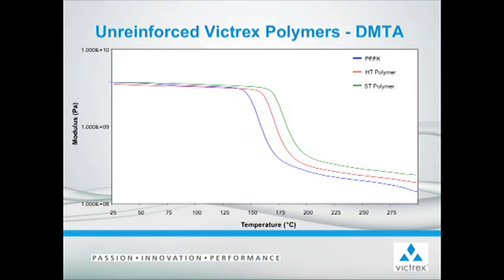This plot illustrates the difference in the glass transition temperatures of our PEEK, HT, and ST polymers. The curves are measured on a DMTA, or Dynamic Mechanical Thermal Analysis machine. The glass transition temperature is a range over which the material softens into a viscous liquid or a rubbery phase. Amorphous materials typically just get more and more fluid above their glass transition, while semicrystalline materials like PEEK, HT, and ST will maintain mechanical properties and stiffness above the glass transition all the way to their melting temperature. If you take a horizontal line starting at a specific modulus and go across the temperature range, you can see how the materials differ and how much additional strength and stiffness is retained when you get above the glass transition temperature for the different materials we have.